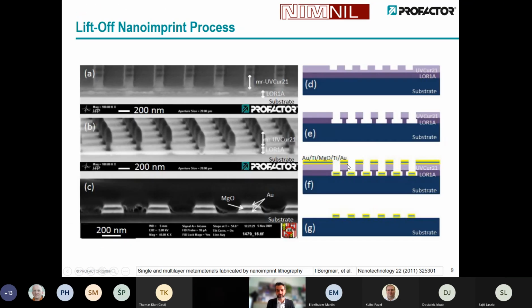And what we did in this project, we developed a nanoimprint process for liftoff, which basically works as you can see, as it's sketched here. So we have a substrate and we have a two-layer resist system. The top one is nanostructured using nanoimprint lithography. And the second one is used for the liftoff in later stage. So the nanostructures are imprinted, the residual layer is removed, and an undercut is created.